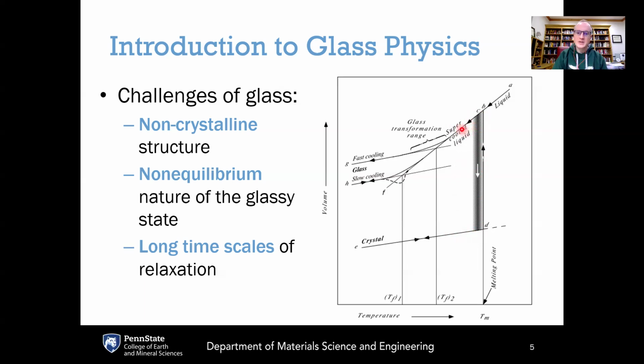To get a glass, we take the supercooled liquid and we continue to cool it. As we continue to cool the supercooled liquid, the viscosity is becoming higher and higher, meaning that it is becoming more and more difficult for the supercooled liquid to flow. So you can think of this as going from a really low viscosity like water to a much higher viscosity like honey. And if you continue to cool it, the viscosity becomes higher and higher and higher. Eventually, the viscosity becomes so high that the time scale that is required for flow becomes longer than your observation time scale for actually observing that flow.